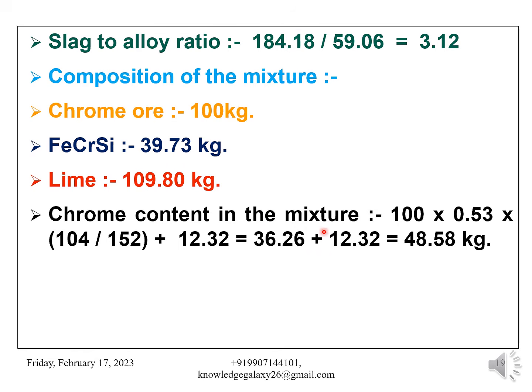Chrome content in the mixture is calculated as 100 into 0.53 into 104 by 152 plus 12.32, which is equal to 36.26 plus 12.32, total comes to 48.58 kg. Total chromium recovery to the alloy is calculated as 42.06 divided by 48.58 into 100, which is equal to 86.58%.